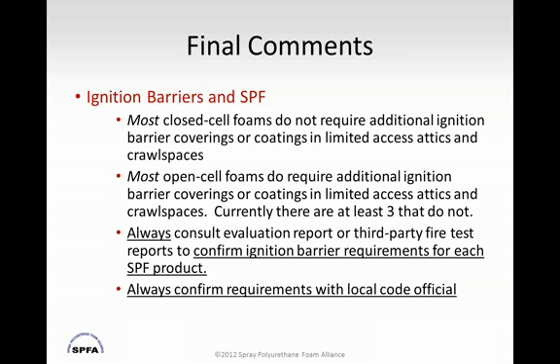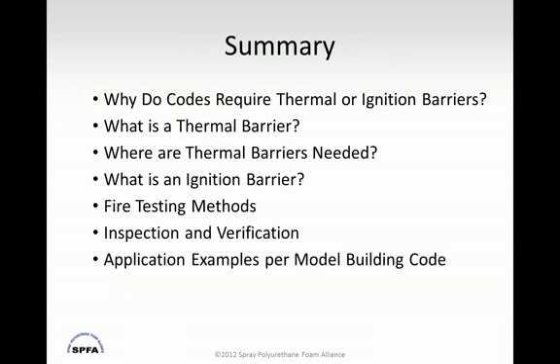The same test has been performed on open cell foams, and what we found out initially in 2009 and 2010 is that most open cell foams did require an initial ignition barrier or thermal barrier covering to pass Appendix X. However, the technology is changing. We've seen some innovation since 2009, and within the past year, we've actually seen that there are 3 open cell foams that have modified their formulations that allow them to be installed in limited access attics and crawl spaces without an ignition barrier coating. It's always important, however, to consult your evaluation report or third-party fire test reports to confirm what the ignition barrier requirements are for each brand of spray foam product that you're using. And finally, it's very important to confirm that ignition barrier requirements are permitted by the local code official. In summary, I think I've covered all these topics, and I'd like to open this up to questions.